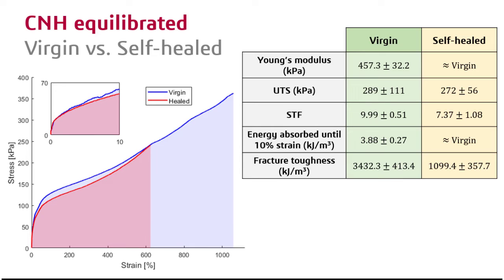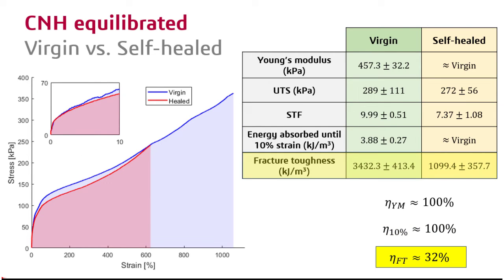The Young's modulus is approximately equal in both cases, as you can see in the graph. This leads to an efficiency of 100% in Young's modulus. Higher differences are observed in the ultimate tensile strength and the strain to failure, as mentioned before. Taking into account the energy absorbed until 10% of strain, the efficiency is about 100%, as it can be seen here. Finally, considering the fracture toughness, the self-healing efficiency is 32%.